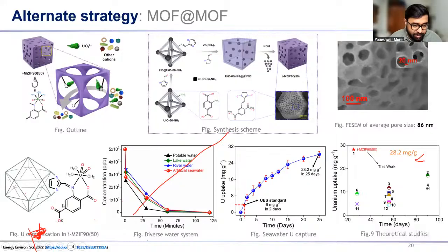You can see on the left hand side, to capture the uranium a particular type of geometry is required. That is this, the uranium, the OH, three water molecules, this oxygen, and this oxygen and nitrogen coordinating, anchoring to the uranyl cation that anchors the uranium. Okay, that is the particular geometry where the uranium can be adsorbed in the MOF. This is a part of the MOF assembly.